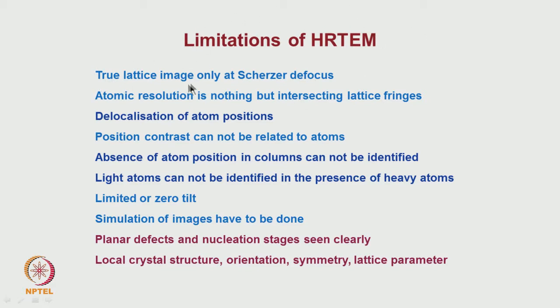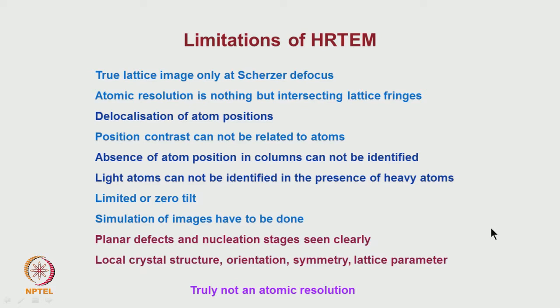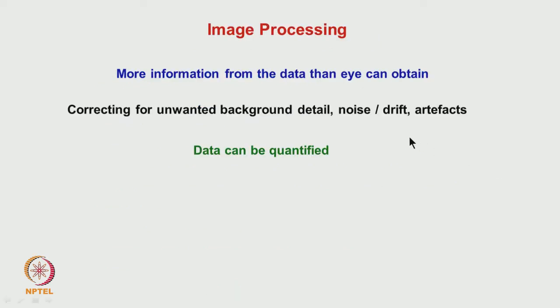There are limitations: the true lattice image is obtained only at Scherzer defocus, though near-Scherzer conditions also give useful images. To determine structure correctly, image matching should be done for multiple defocus values, accounting for how the microscope affects the image away from defocus. Delocalization of atom positions must also be considered. The key point is that the image is not an atomic resolution picture without simulation — image simulation is a must.